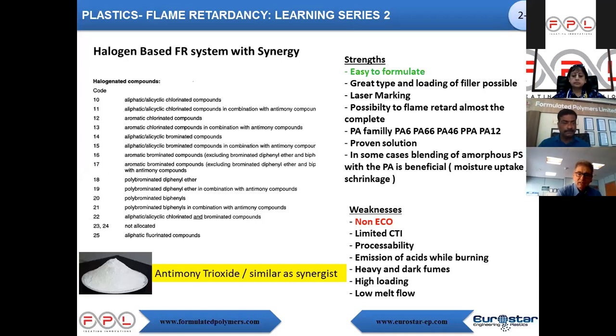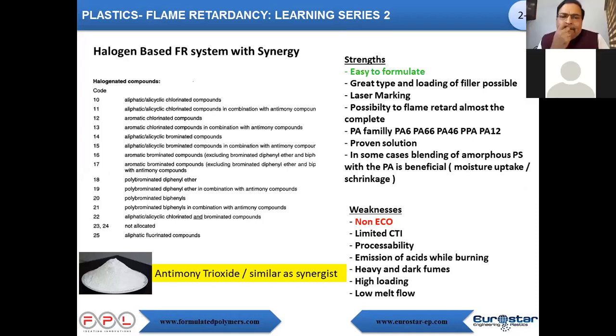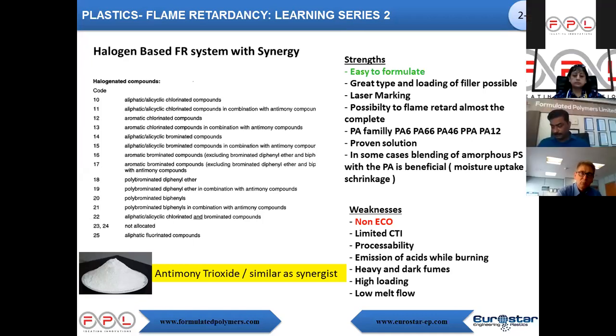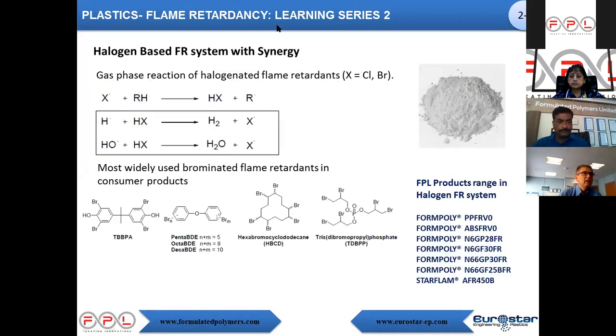You need quite a high loading of flame retardant material. Let's say if you make the sum of the flame retardant system with antimony trioxide, meaning its synergist, it's above 20%. So it has a real impact on mechanical properties. In some cases, it reduces the melt flow. So I will go a bit into the systems, but not going too much into details about chemistry.